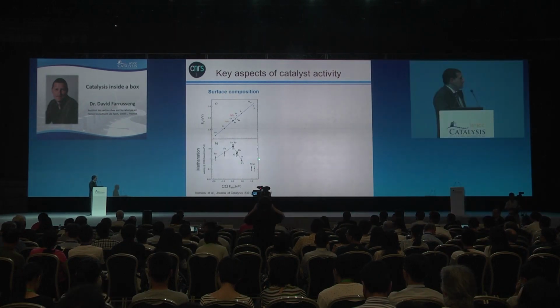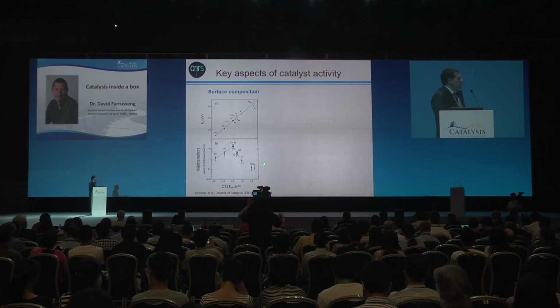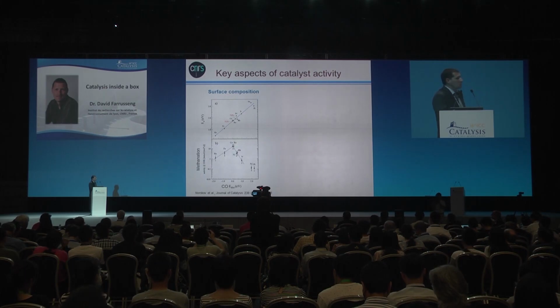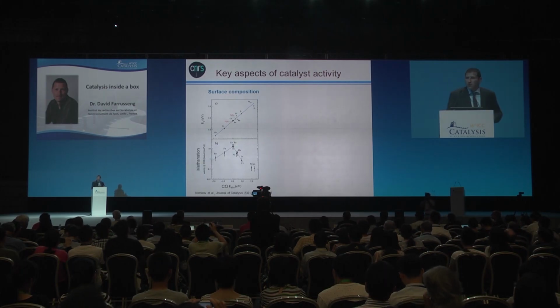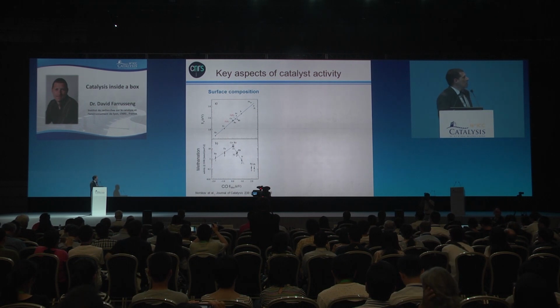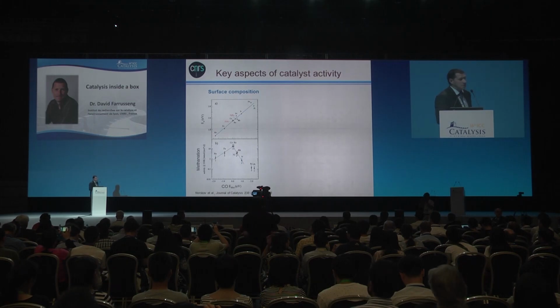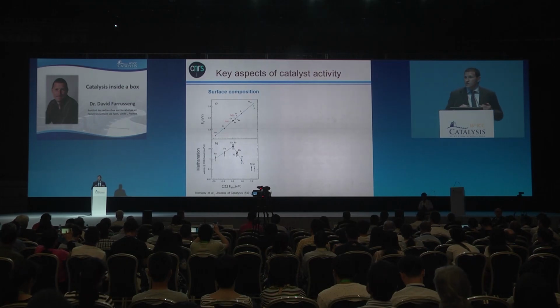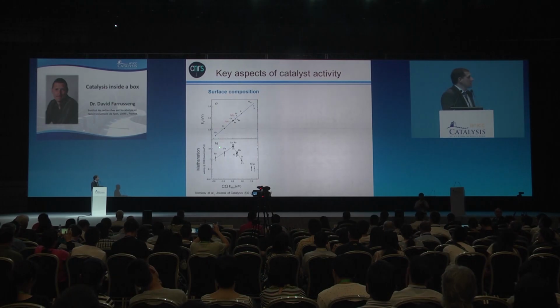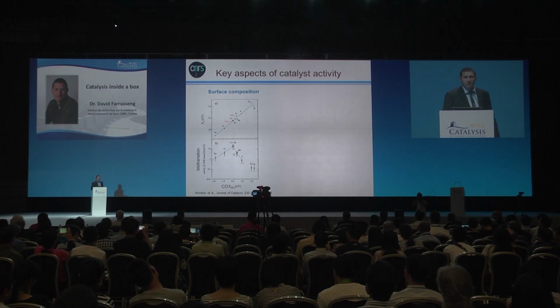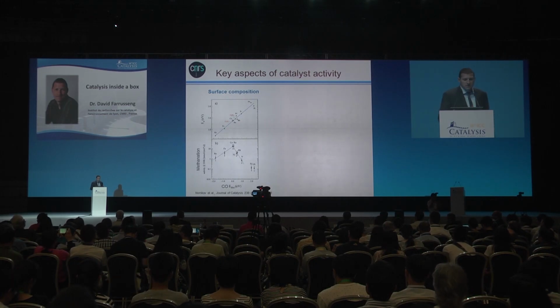So when you have a low interaction with metal particles, you have a low activity. On the other hand, for rhenium or iron, if it is too strongly adsorbed, you also have a low activity. It is only for medium stability metals here that you get the highest activity. What is also important to remember is that if you select two metals that are on different sides of the volcano curve and mix them together, you also get a very highly active catalyst.